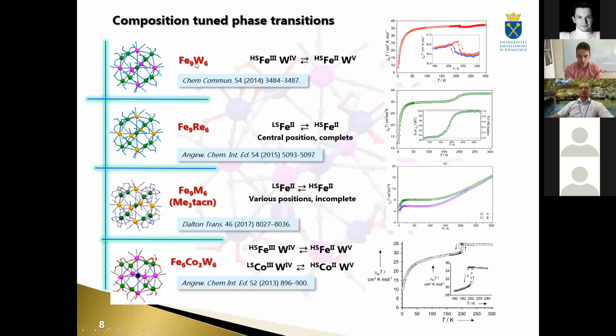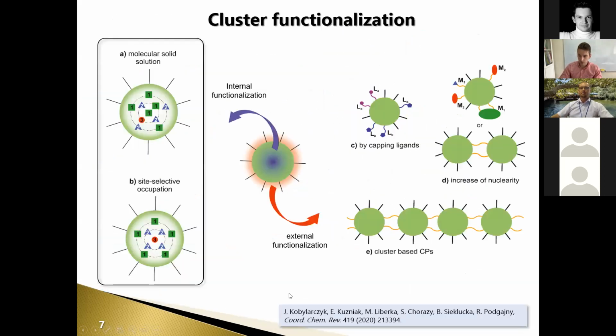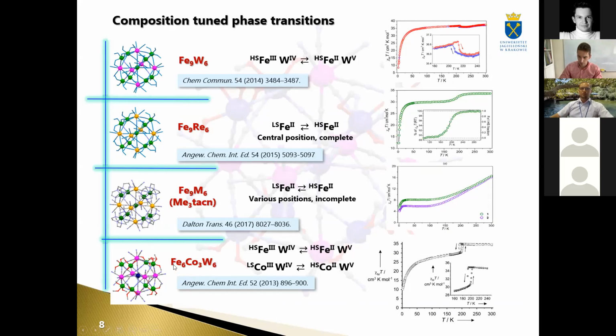Depending on the composition of the cluster, we can go through the bimetallic cluster, for example, iron tungsten, iron rhenium, and trimetallic composition. This cluster can undergo a reversible phase transition, which can be coupled with intermetallic electron transfer, governed by temperature, as well as spin crossover, and the trimetallic composition can host such properties in a more sophisticated and complicated manner. And here, these magnetic curves just exemplify that in each of such compositions we can have a phase transition, but they have very different characteristics, because they are based on various processes.